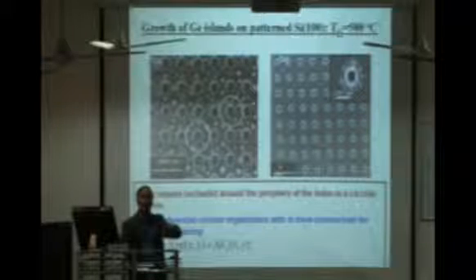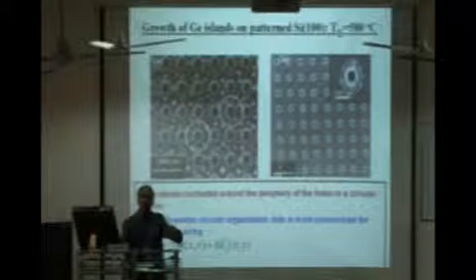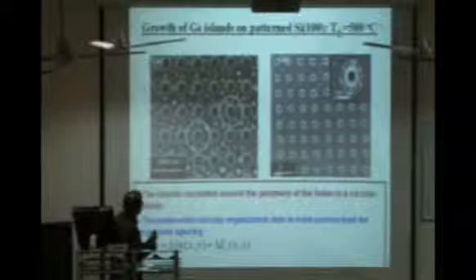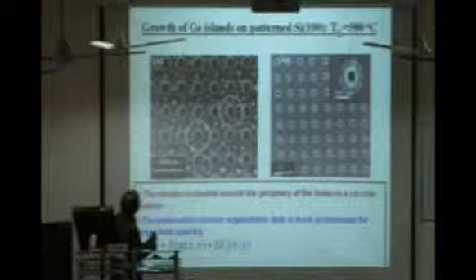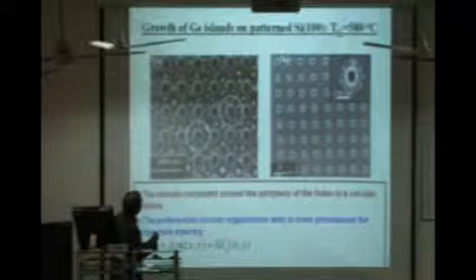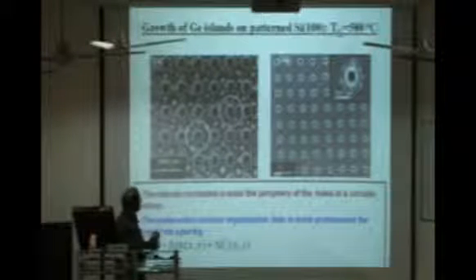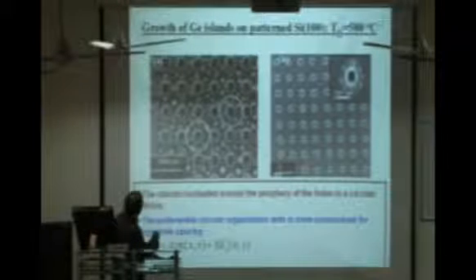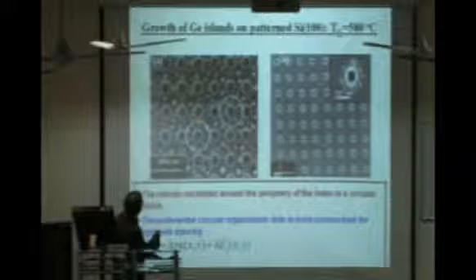But to our surprise, we see something different, because this depends basically upon the aspect ratio of the hole to the so-called period. In fact, what we see is that instead of nucleating in the hole, these quantum dots are nucleating along the periphery of these holes. And as you see, there is a kind of circular periodicity. Of course, there is some randomness between two holes or two dots. But if you just consider one of the dots, there is a very good circular periodicity.